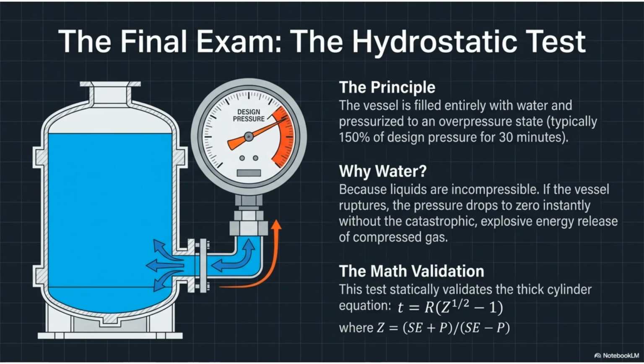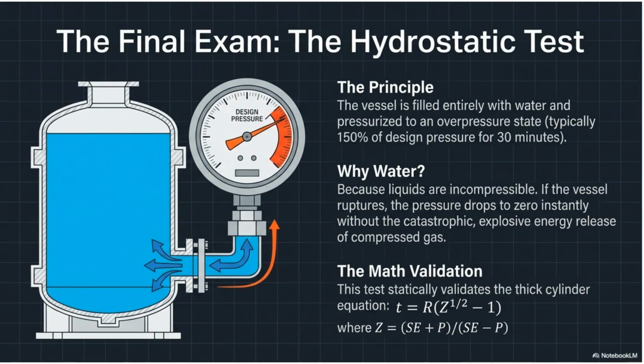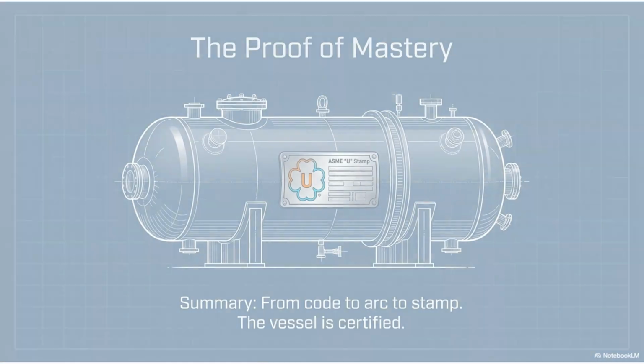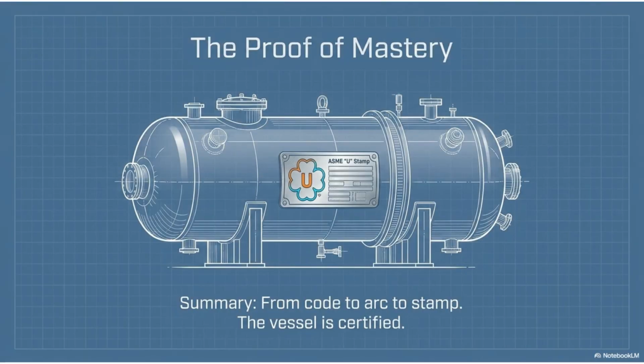The vessel is filled with water and pressurized to an overpressure state, typically 150% of design pressure, for 30 minutes. We use water because liquids are incompressible. If the vessel ruptures, the pressure instantly drops to zero, preventing the catastrophic explosive energy release of compressed gas. This marks the proof of mastery, going from code to arc to stamp, and the vessel is certified.